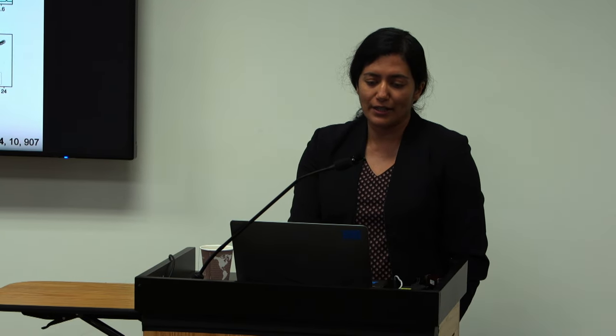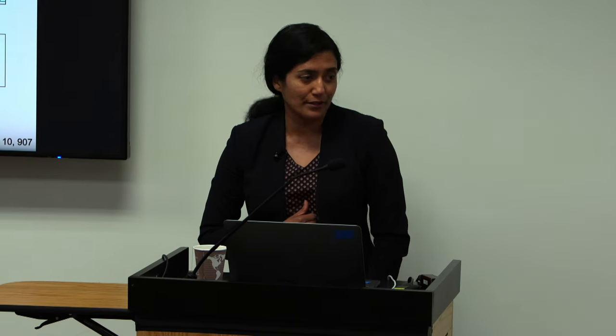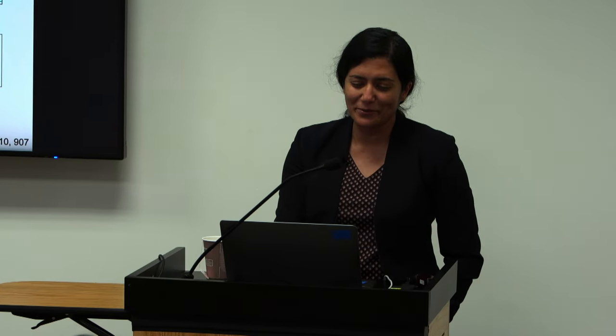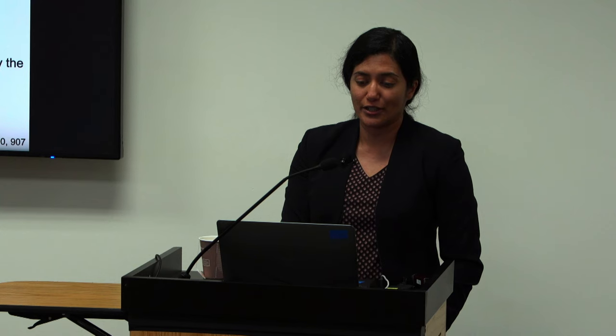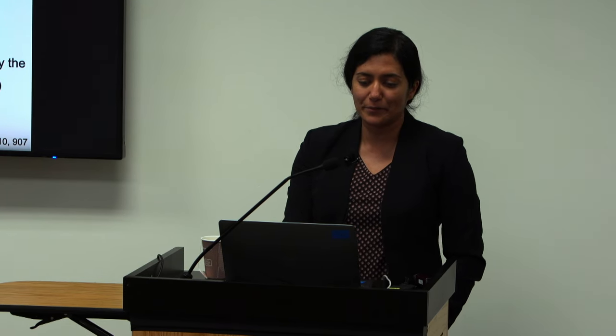So Julian did this beautiful study using only single crystals so that we don't have to take into account any issues with grain boundaries. He made electronic contact with carbon electrodes. It's a very careful study to make sure that perovskite is not decomposed. He also made contact with silver iodide electrodes to measure ionic conductivity. And I'll just summarize all of this with just this picture here, which is the picture that we are developing, which shows the breathing of iodine gas.